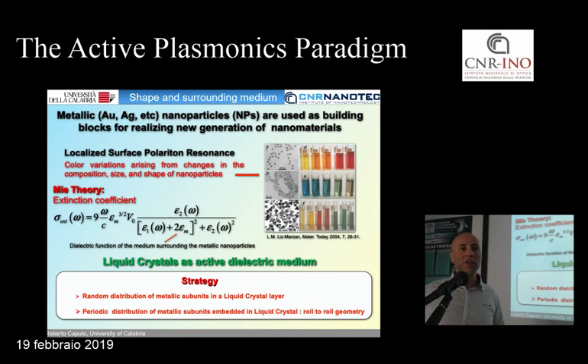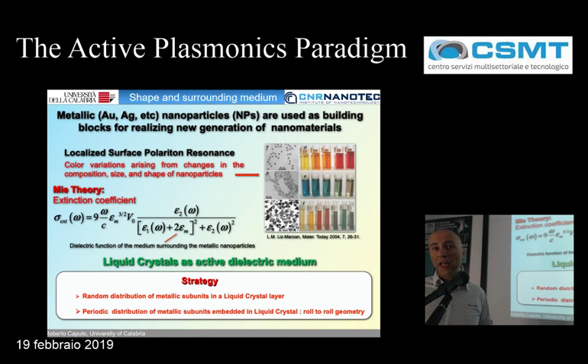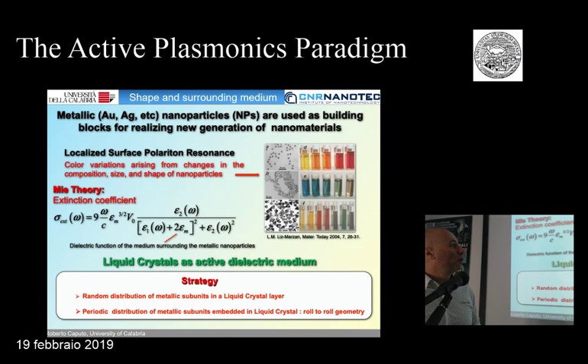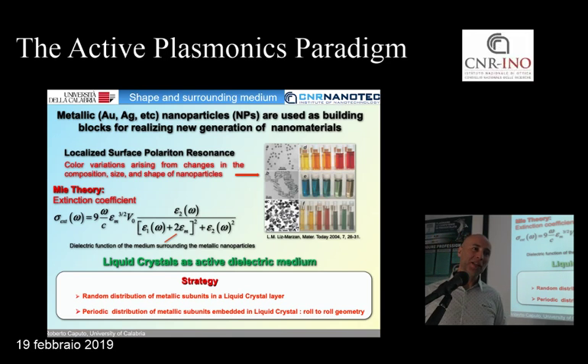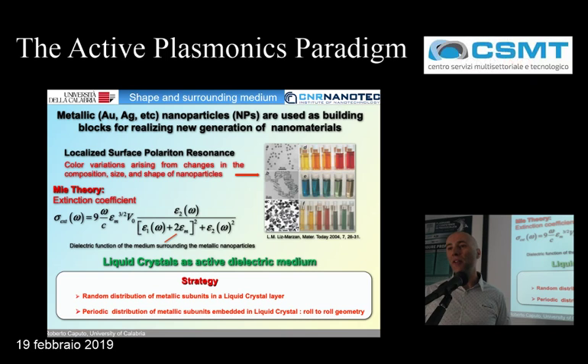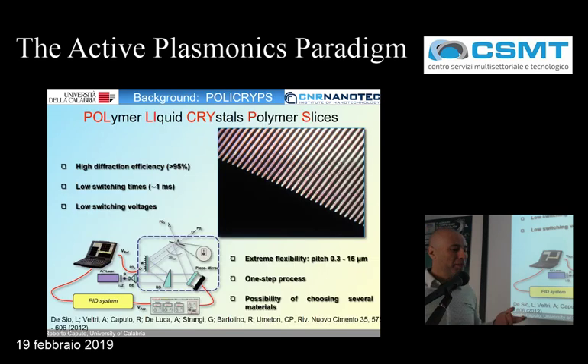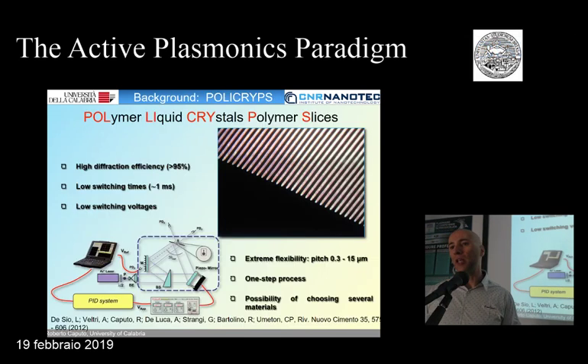And this is what we started exploring in 2009. As I said, we started switching from typical photonics to plasmonics. And we used as a surrounding medium what was the natural medium for us, because we are a community studying liquid crystals. So the basic medium was liquid crystals, because it's an extraordinary medium for changing the refractive index of the material surrounding the particles. So the main way we started was by using what we were good at doing until that point.